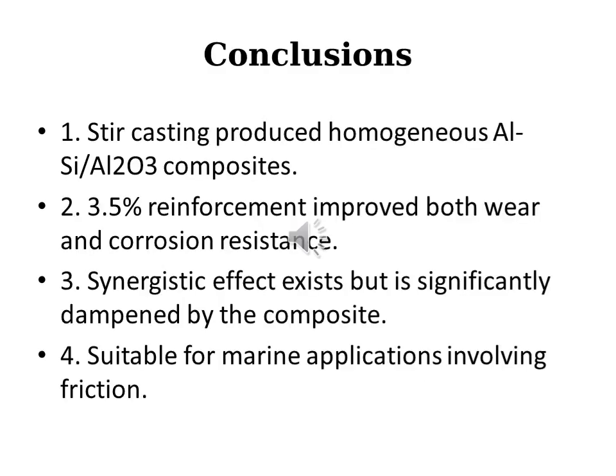In slide 10, conclusion. To conclude our presentation, stir casting successfully produced homogeneous composites. The reinforcement improved both wear and corrosion resistance significantly, while the synergistic effect that exists is significantly dampened by the presence of the ceramic reinforcement. Therefore, the composite is highly suitable for marine applications involving friction.